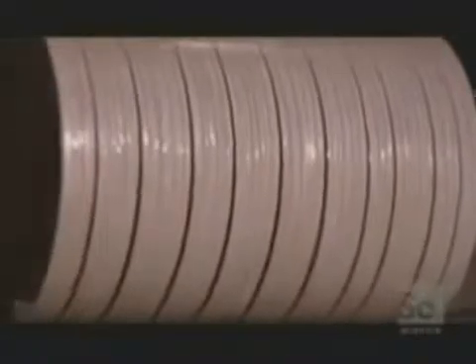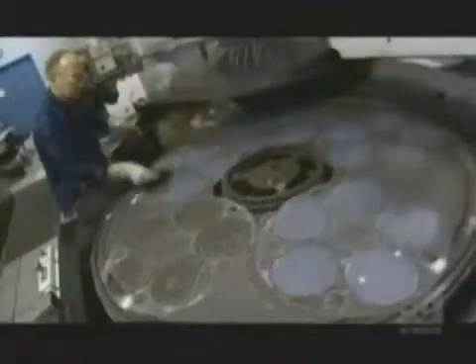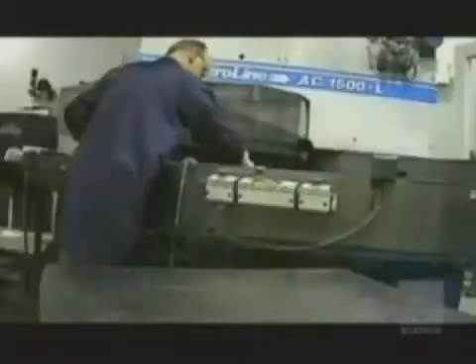Once cut, there are microscopic marks left on the wafer surface, so it's time for a buffing using a process called lapping. After a twirl in this high-powered polisher, they are still not smooth enough. So they're given yet another buff using a chemical process. The result is wafers of silicon with a surface roughness of less than 1/1,000,000th of a millimeter. Buffed to a sheen, they're finally ready for etching with the circuit design.